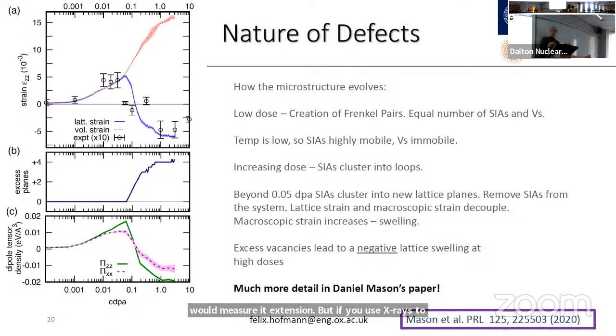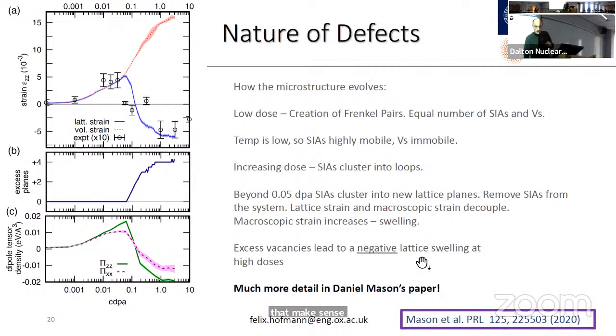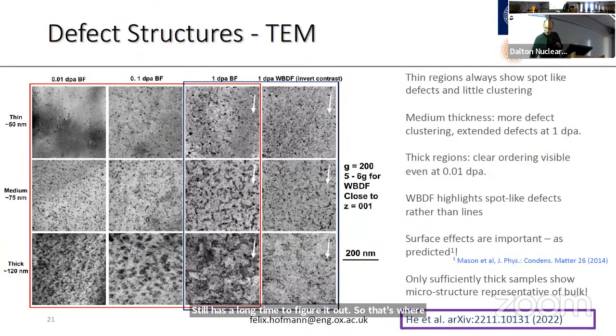The reason is that these extra atomic planes effectively are strain-free. Yeah, they give you a change in the overall outside dimension, but they do not show up in your lattice strain because your lattice strain is now dominated by the retained vacancies. Does that make sense? This took us a long time to figure out. So that's why we see this negative lattice swelling.